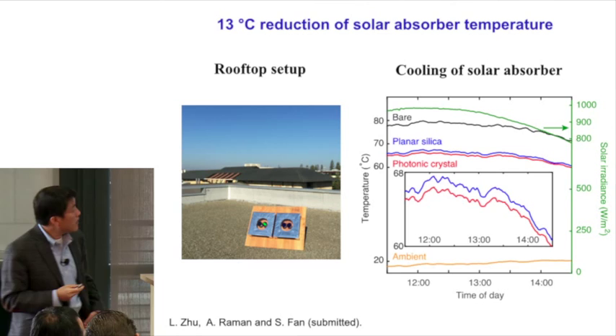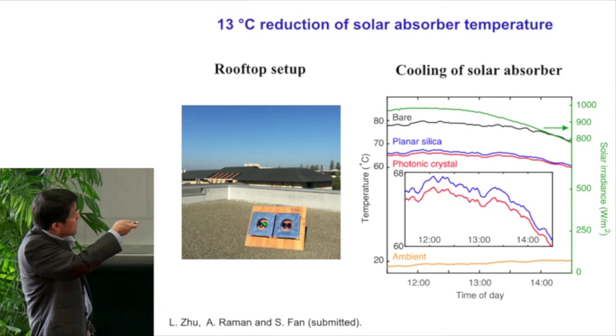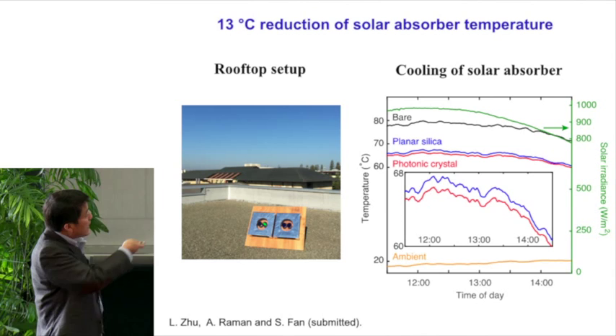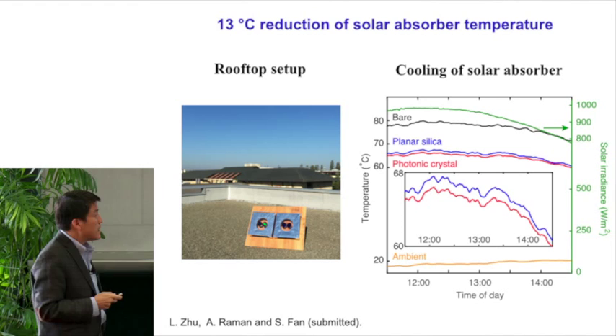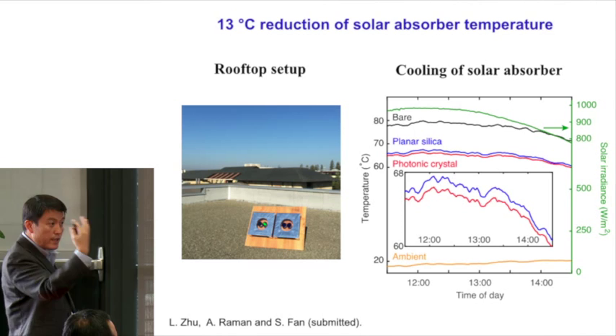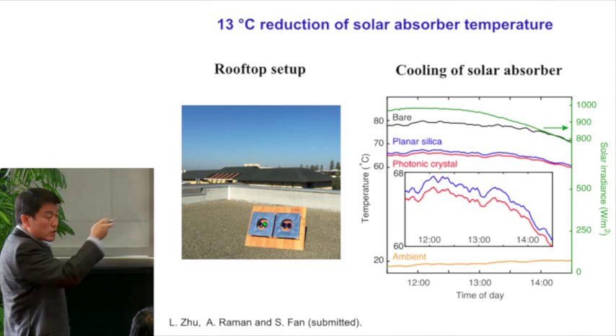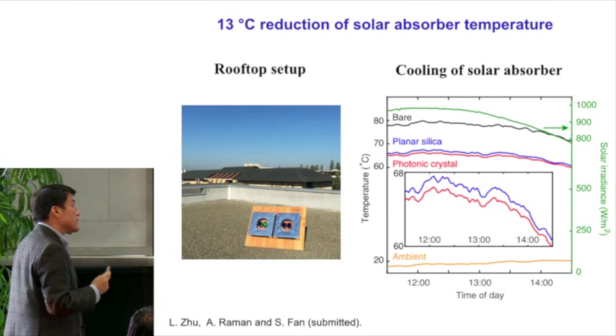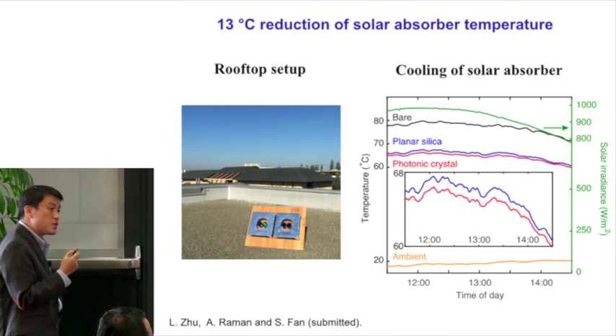Again, we compare all these structures on a roof. So we compare the planar silica structure and the photonic crystal structure in one of these little chambers, and as a comparison, in the other chamber, we put in two bare silicon samples. And again, under the sun, you can see the bare silicon sample actually heats up very substantially due to the solar absorption. Both the planar silica sample and the photonic crystal sample, on the other hand, have a much lower temperature. And also, out of the three structures, the photonic crystal sample consistently has the lowest temperature in spite of the fact that it has the highest solar absorption.